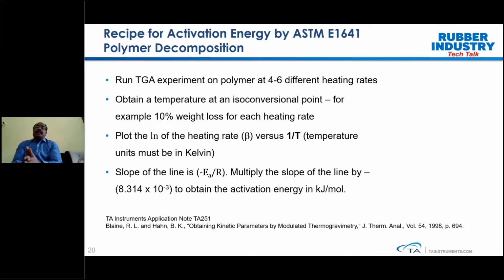And what we do is basically we capture the conversion rate, which is basically as the ASTM technique, at 4 to 6 different heating rates, and then we plot the heating rates versus inverse of temperature. The slope is basically giving the activation energy divided by the gas constant. That multiplied by the gas constant will give you the activation energy. So if you wish to understand the activation energy of your decomposition, basically you would be doing these studies.